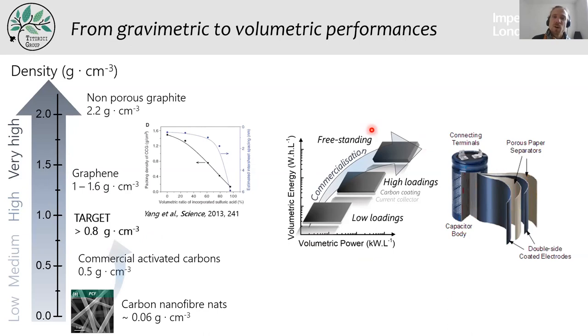And here is a scheme of what we are trying to achieve for commercialization. Here we have low loading, where you can see the carbon material on the top of the aluminum foil. And the higher the loading, then the higher the proportion of the carbon until it actually becomes a freestanding electrode. And so all the materials that we test are actually freestanding in this case.